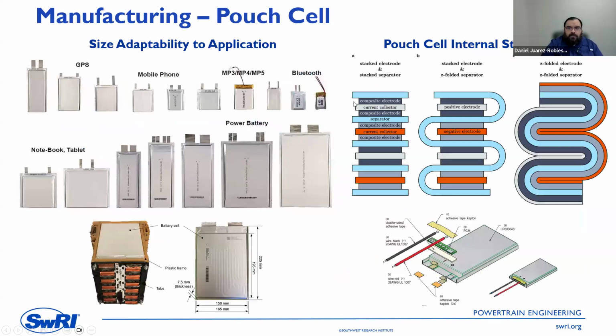There are different formats on the pouch cell. One approach is you cut the small electrodes and then you stack them. Here you can see either the positive or the negative electrode, and in the middle you have the separator. Then you introduce the next one. In this case, one of the electrodes is double layer, and some of the electrodes at the end is just a single layer. A different approach is having a single separator along the whole cell.